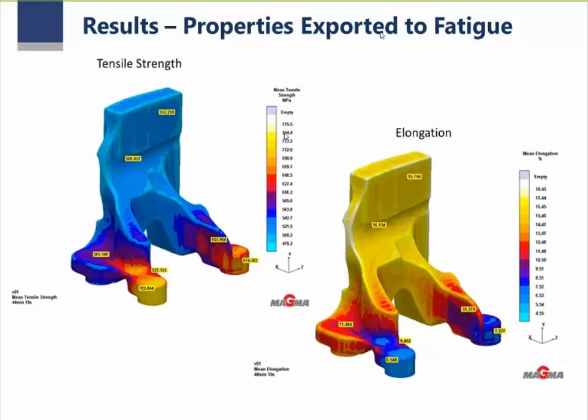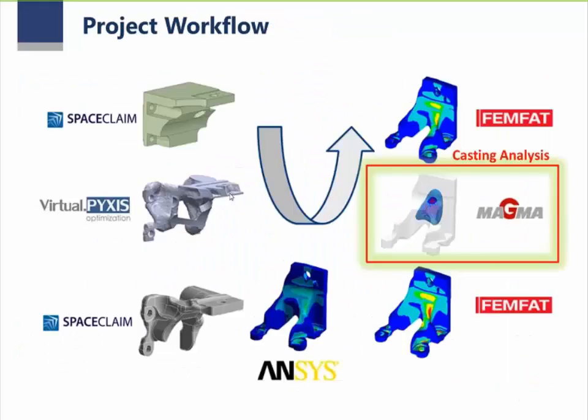The main situation is getting the tensile strength. So here you see some variation. For example, for this region you are getting higher tensile strength, and for this region you are getting lower tensile strength. So for example, from our critical region, which is around here, you have around 500, which in this case is sometimes even higher than, just going back here a little bit to remind you, this is our material properties.